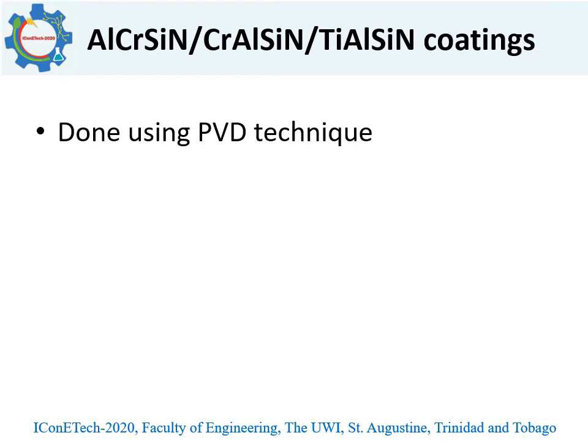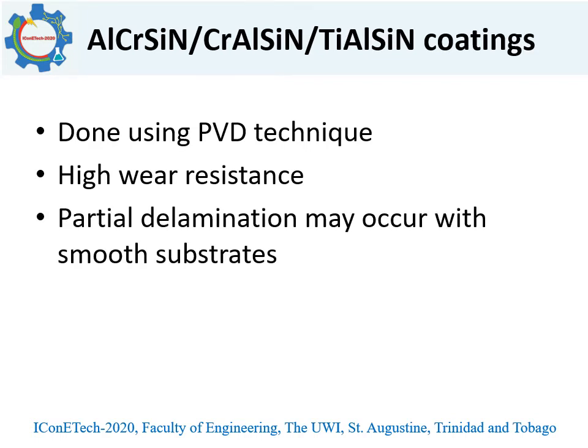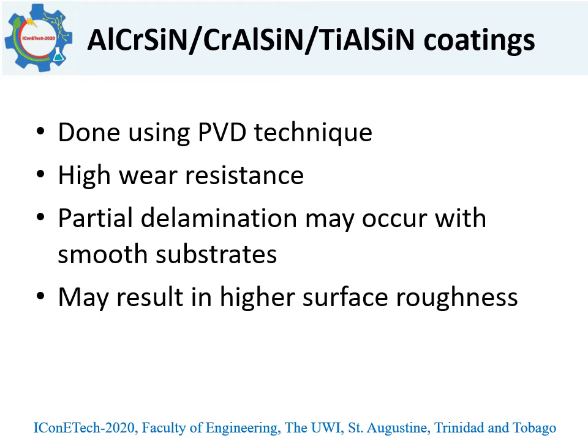These are some of the coatings: aluminum chromium silicon nitride and titanium aluminum silicon nitride coatings, generally done using the PVD technique, physical vapor deposition, and they contribute to high wear resistance. But again, the same problem of delamination comes, particularly when you deal with a substrate which is extremely smooth. Also, sometimes it has been noticed that multi-layer coatings such as these resulted in higher surface roughness of the machined components.